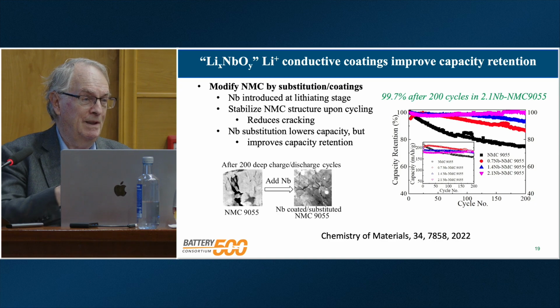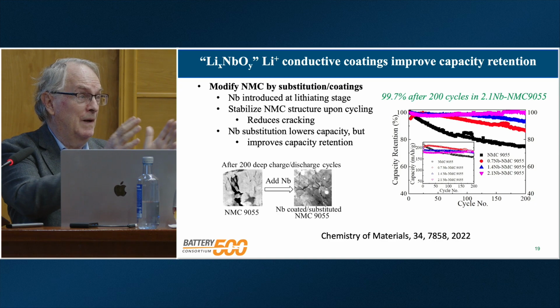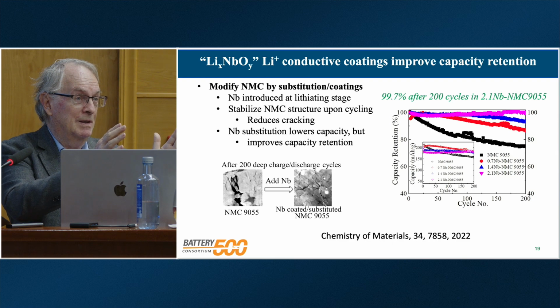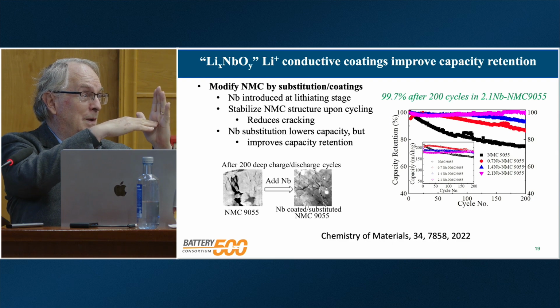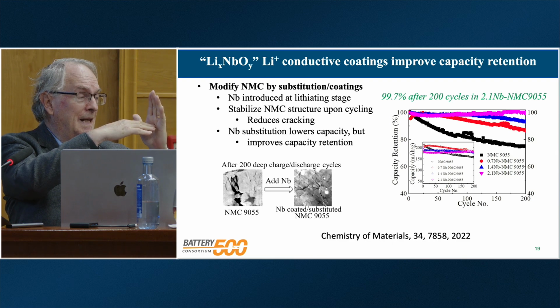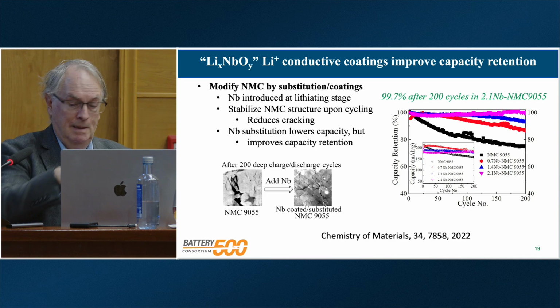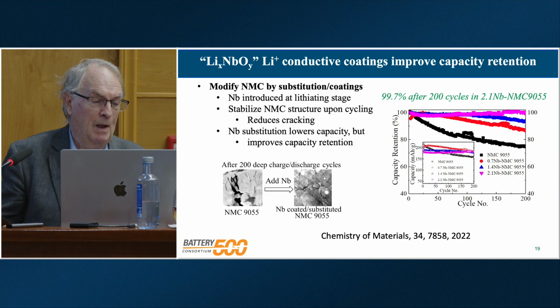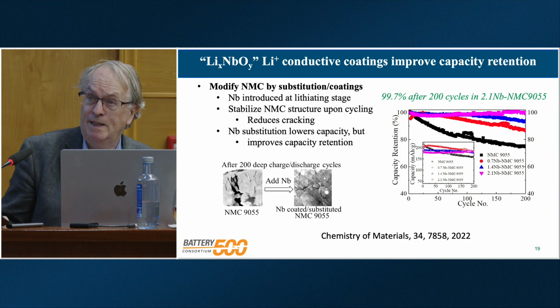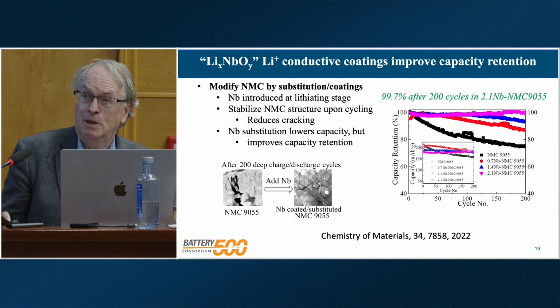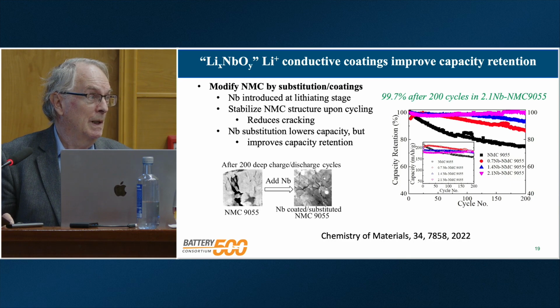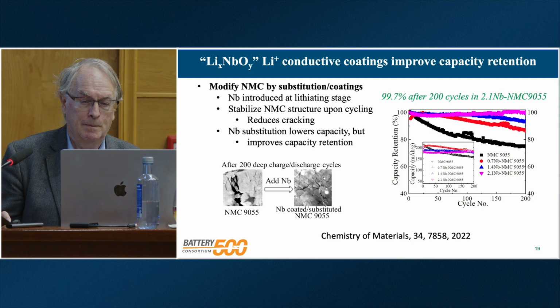So remember, even in these layered materials, they expand by maybe 5 or 10%. We've got some of the crystals this way, some this way, if they expand, they then crack those meatballs. And you can see on the plot there with no niobium, big cracks. On the right-hand side there, with niobium, the cracks are much, much smaller. So we're actually preventing the cracking of those meatballs. And this is with a standard